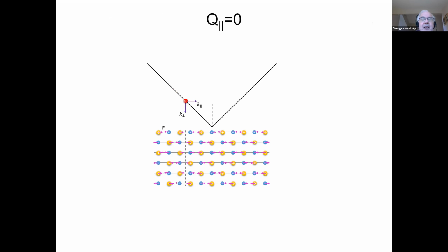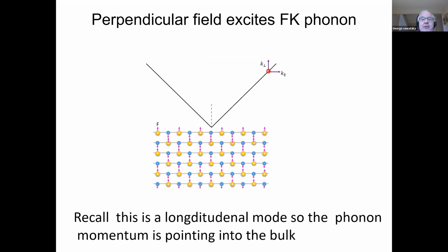There. If you now go to the end, way out here, all you have left then is that you've left behind a time-dependent perpendicular field, right? And that time-dependent perpendicular field is the one that excites that phonon. And that phonon, if you do a Fourier transform of that, it has that frequency component in it, and it will excite that phonon. It has a very strong coupling to it.